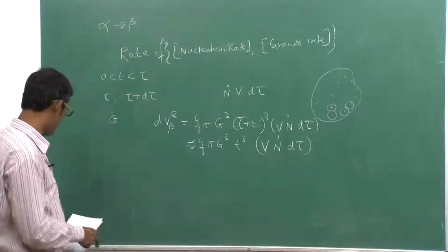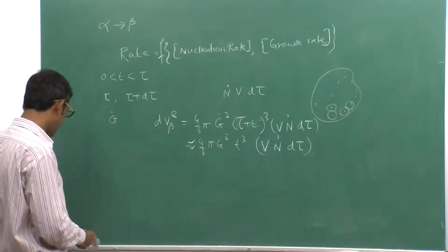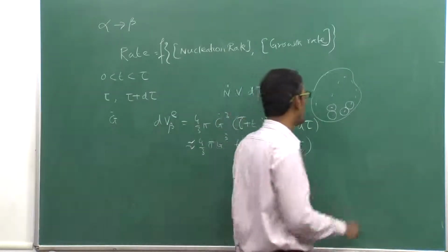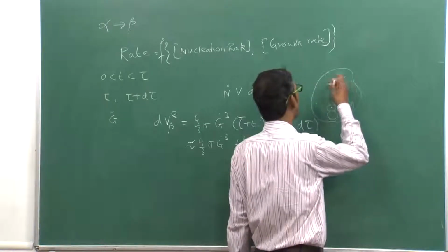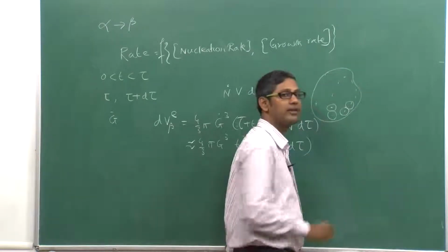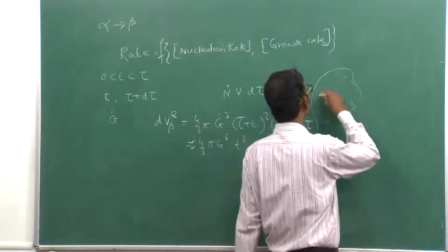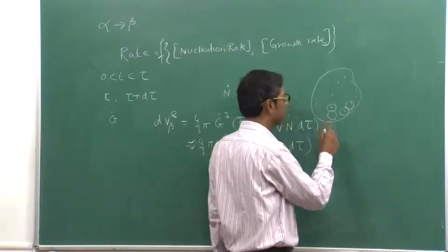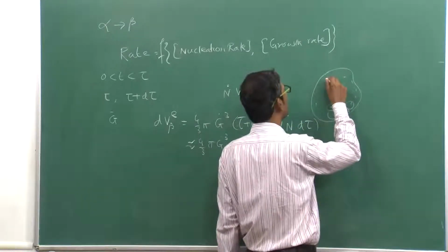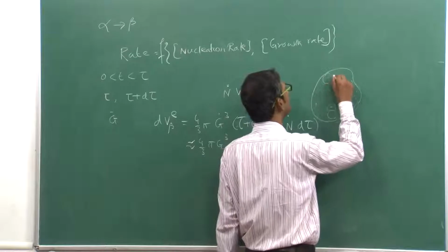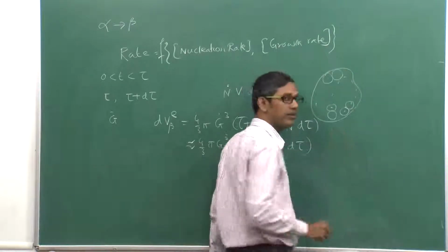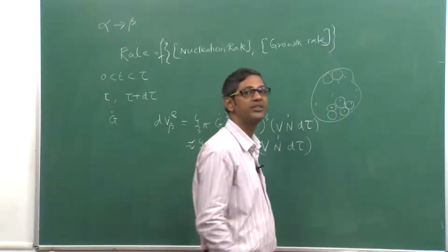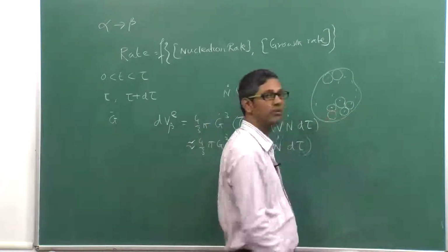The second assumption is that we always assume these nuclei are growing only in the untransformed regions. Suppose you have a grain which is not yet fully transformed, and a grain which has already been transformed. The likelihood is that a nucleus sitting here will grow much faster than a nucleus sitting there, because a lot of strain energy has already been reduced by the formation of those nuclei.